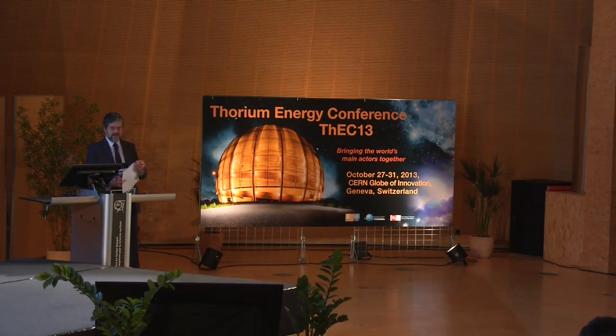The materials. Well, Hastelloy N was proven during the molten salt reactor experiment as sufficiently corrosion resistant. But there is a problem. The molten salt reactor experiment did not run for very high power for very long, and it did not really test the embrittlement aspects of Hastelloy N. It actually needs to be modified to reduce embrittlement in the neutron radiation field of the core.